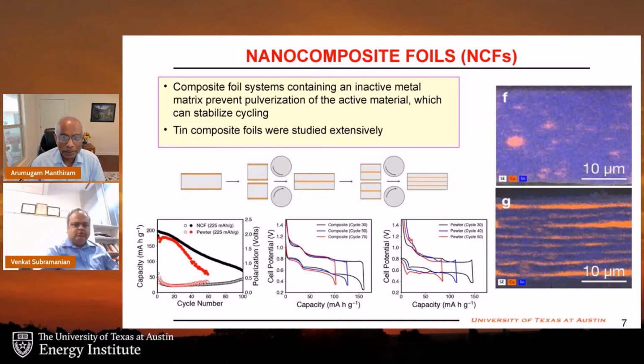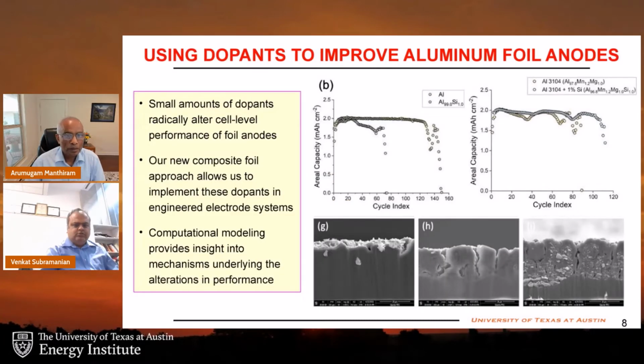If you don't do that, then you will have this kind of segregation, which is going to create a lot of volume changes and performance degradation. So one example I show here, aluminum versus 1% silicon doping. If you see that, you see a much bigger improvement in the capacity.